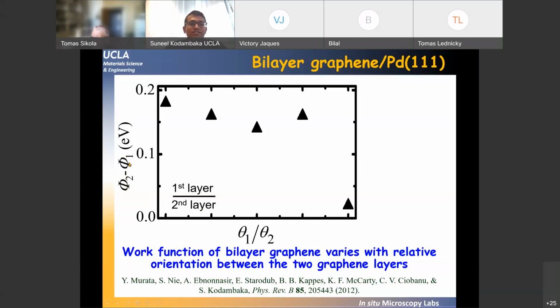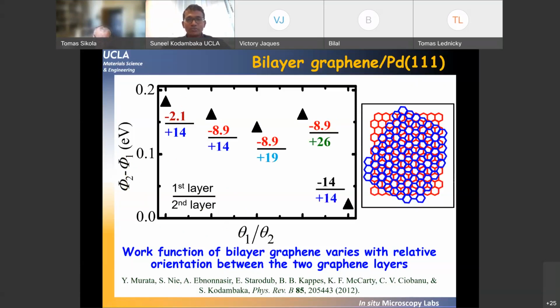So this is the difference in the work functions within the bilayer graphene as a function of relative orientations of the two layers in this bilayer graphene. And the numbers here correspond to the relative orientations of graphene with respect to palladium-111. So as you can see, this is the only one that has the ideal graphene single crystal orientation. All the other ones are misoriented bilayers. Each layer is oriented differently with respect to the other layer. And you see this variation within the work functions by up to 0.2 eV. So even within the bilayer, you have a huge variation in the work function.